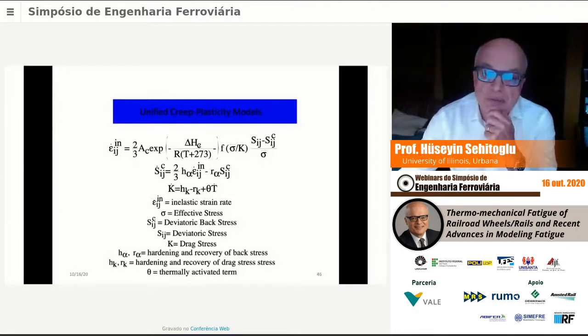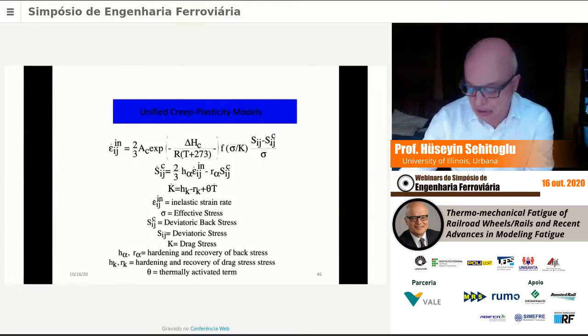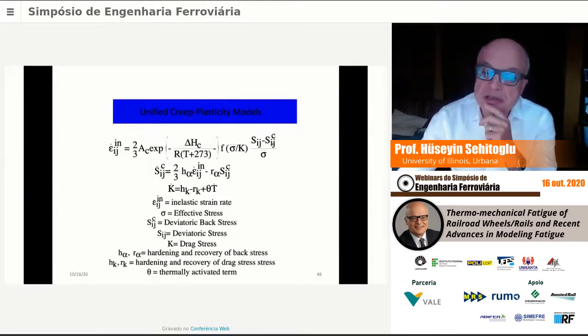Now, that function is this function here. And this is the stress, deviatoric stress. And this is activation energy. This is temperature. This is inelastic strain rate. This is back stress, which accounts for the Bauschinger effect, but it also deals with the direction of flow in the case of hold times and things like that.